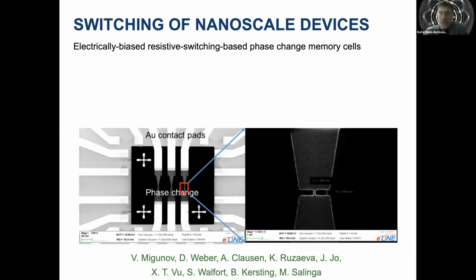And now, very briefly, I'd like to touch on the second and third topics before concluding. The second topic is switching of nanoscale devices in situ in the TEM. So here, as an example, I'd like to show phase change memory cells, which are small structures, again, only a few hundred nanometers in size, in which an electrical current can be used to change the device from an amorphous state to a crystalline state.